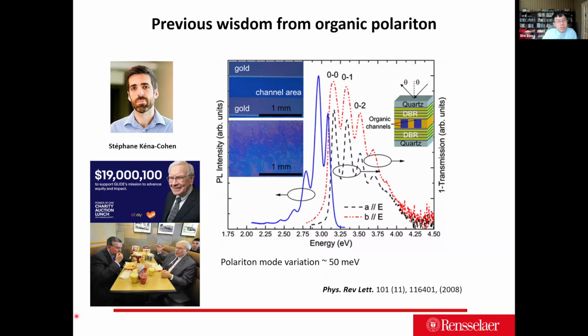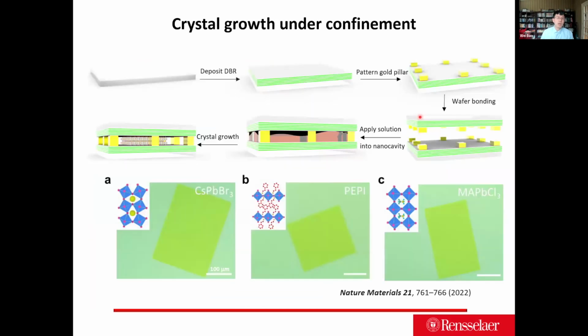So I got a lot of inspiration from the discussion, and I also think the polariton mode variation of 50 meV is coming from the relatively not so well-designed process of bonding the two DBR chips together. The problem is coming from the DBR fabrication and how you bond them together. So I went back to Nebraska and redesigned the experiment. Instead of using a small chip, we use a big wafer. We use a really big 6-inch wafer and deposit the DBR really carefully.